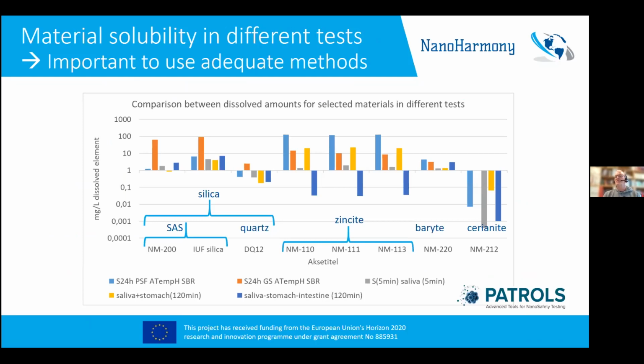I will not go much into details here, but I'll just show you an example of the differences you get in solubility when you use different methods. And here you see synthetic amorphous silica materials, quartz, zinc oxide materials, barium sulfate, and cerium oxide. Clearly you can see quite different levels of solubility in the different experiments done here, for example in blue and orange, the 24-hour dissolution in phagolysosomal fluid versus the Gamble solution.